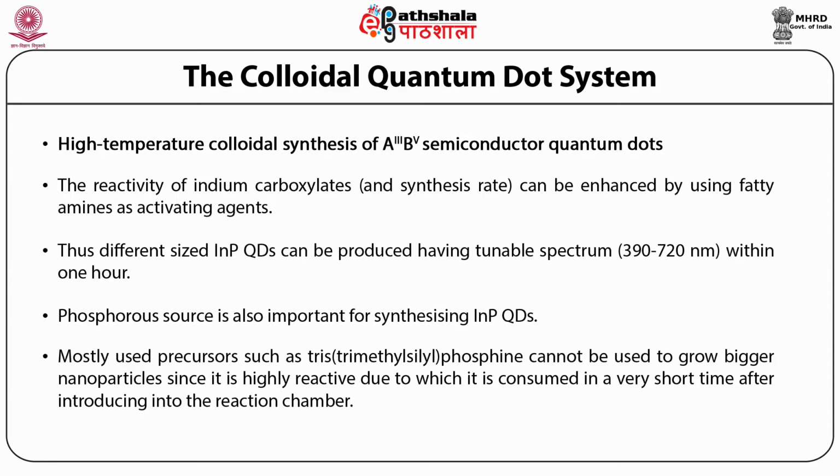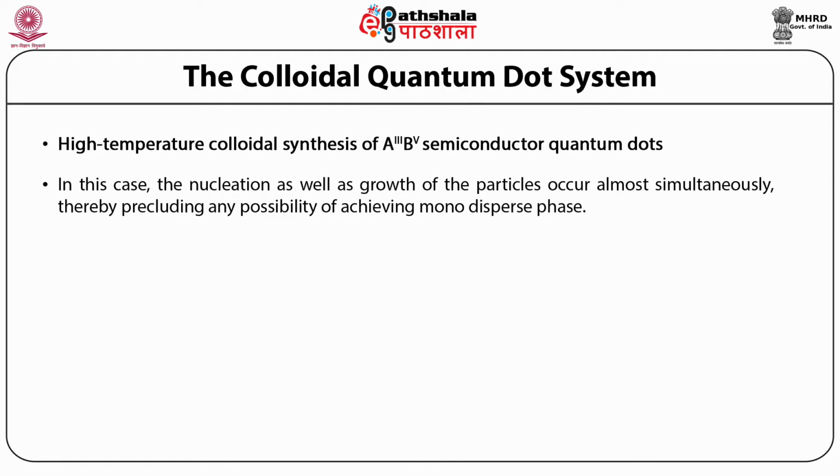Mostly used precursors, such as tris(trimethylsilyl)phosphine, cannot be used to grow bigger nanoparticles, since it is highly reactive, due to which it is consumed in a very short time after introducing into the reaction chamber. In this case, the nucleation as well as the growth of nanoparticles occur almost simultaneously, thereby precluding any possibility of